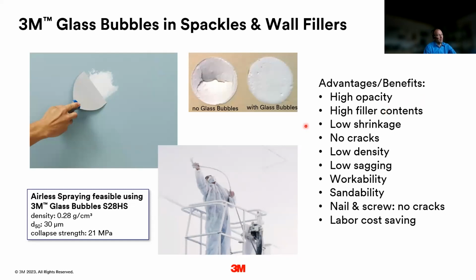That allows us to formulate materials that have virtually zero shrinkage but are still workable. So you can apply a wall filler that does not shrink and therefore does not form any cracks, like in this example of a standard formulation without bubbles, basically only calcium carbonate. So you don't need to rework again. It's also easy to sand because of the bubbles. You can even drive nails and screws into such a material without cracking. Finally, it is very easy to apply, and because less rework is needed, it is time efficient and saves labor cost.